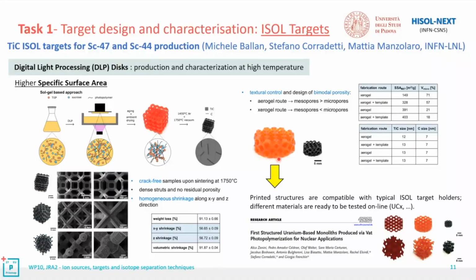This is the sample as fired, and this is the sample after thermal treatment. So we obtain completely crack-free samples after thermal treatment, and we register homogeneous shrinkage along the Cartesian axis. The good point is that we can obtain the structure that we want, so it can be deeply optimized for the proton beam, for the primary beam that you have in your facility.